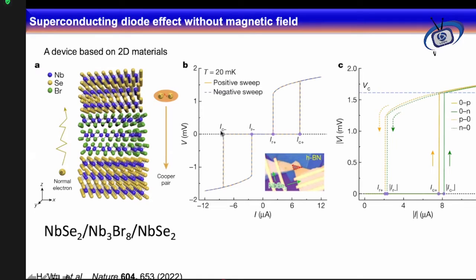And when they plot it with the absolute values, meaning that they have, you can say, folded this IV curve, then they can see that there is a clear difference between the positive current and the negative current. So it means that this is also a diode, and this diode is a Josephson diode.